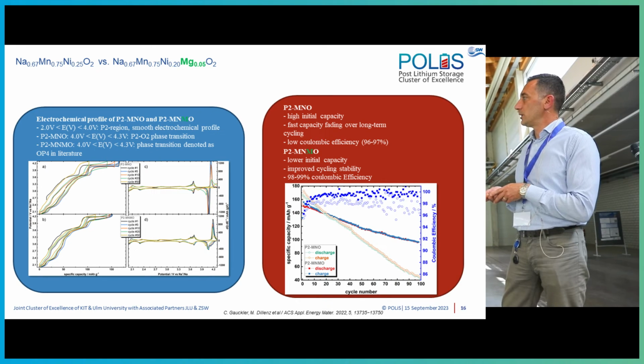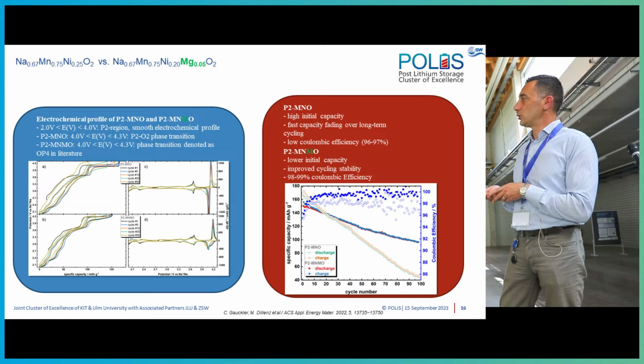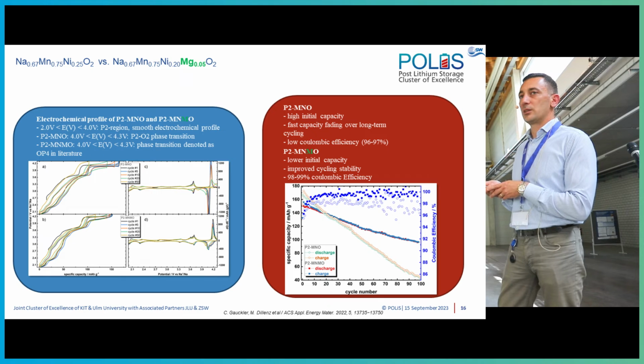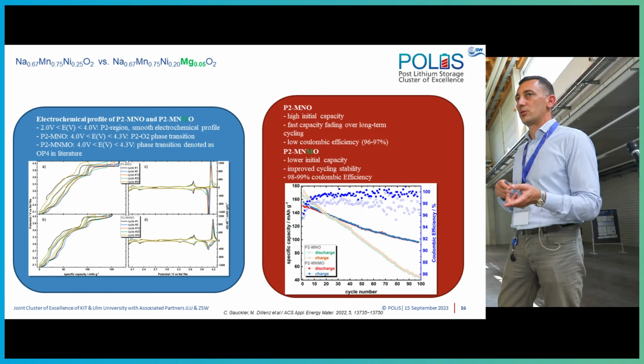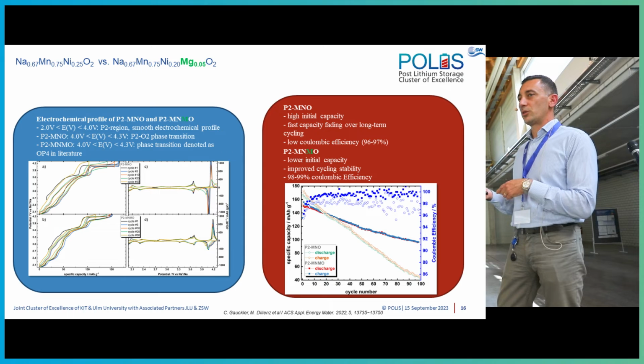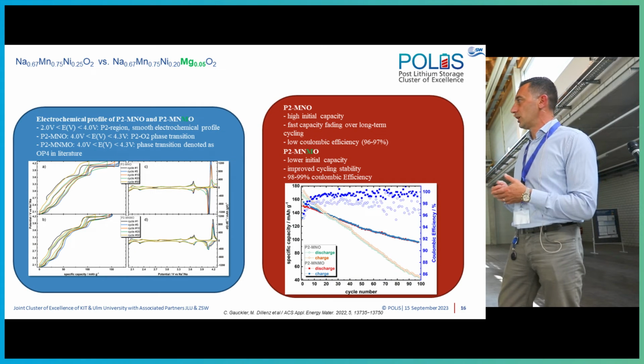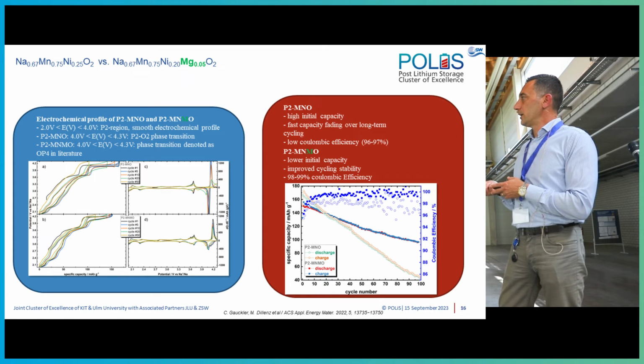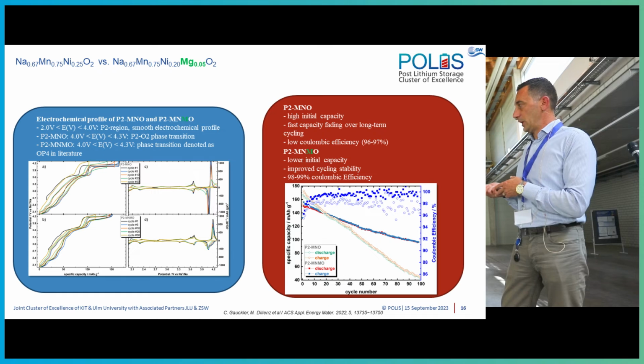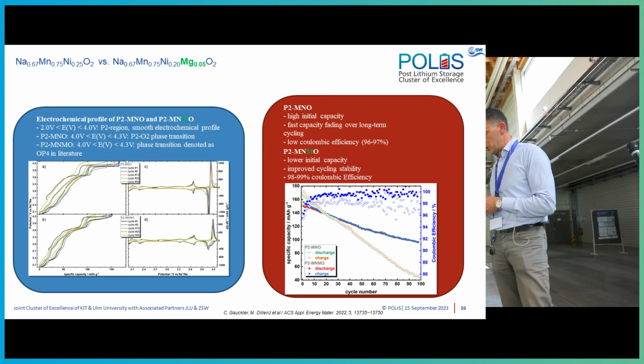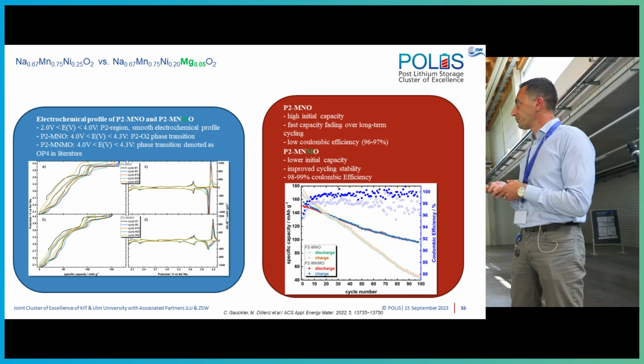The doped material is different. The plateau is shorter. Of course, we have a little less capacity because we are replacing part of the nickel with magnesium. Now, nickel is redox active, magnesium is not. So some sodium will be trapped just because magnesium cannot change its oxidation state in this case. But anyway, the plateau is shorter, and what we see in the differential plot is that actually the peak is broader, very much less defined.